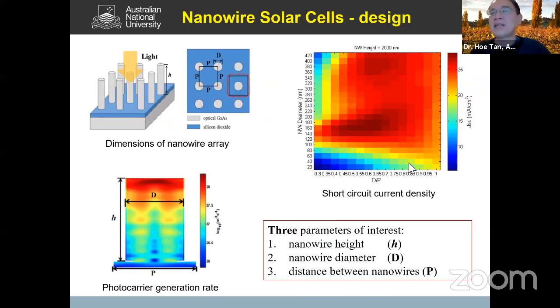Before I show you an example of our device made by this selective area growth nanowire solar cell, what we want to do is see what the optimum dimension is for a nanowire solar cell. Shown here is the absorption intensity of the nanowire. This is a 2 micron nanowire, and as you can see here, most of the absorption is in the top half. So really, you don't need to grow very long nanowires. You'll be wasting your material. You need to grow about 2 or 3 microns. That's more than enough to absorb essentially all the sunlight that shines on it.